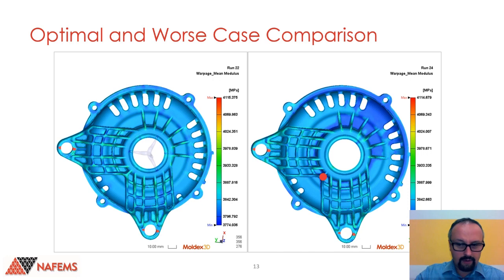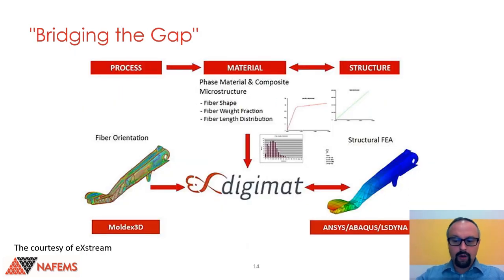And as we can see here, there is a clear difference between the optimal and the worst setting. We can see it in this area. These two are the results of the E-modulus after the molding, the values of the mean modulus in our part. And as we can see, we have a more uniform distribution of the modulus value for our optimal setting. That's the reason it is optimal. So at this point, we know that we need to perform our frequency response analysis, and we have already found the best fiber orientation for the geometry we have designed. But there is still a gap to be bridged. Namely, we need to transfer the results of our injection molding simulation to the input of our structural analysis.